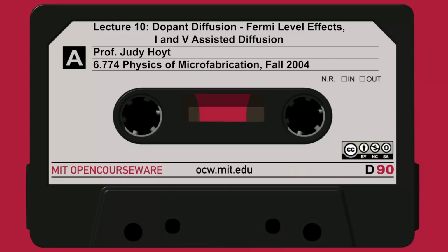By the way, I should say that segregation coefficients, the ratio of some species on one side of an interface to another material on the other side of the interface, sound trivial, but in practice, it's very hard to measure. You might say, well, why don't you just use SIMS? Just profile through the sample and measure the concentration on this side and the concentration on that side. Well, a lot of techniques like SIMS near an interface don't perform very well. Because as you get close to the interface, you're changing the material and the sputter rate starts to change. All the assumptions that you need to make in SIMS tend to be degraded to a certain extent. So you would think we have perfect numbers for this, but we don't. We have rough numbers. And these are the rough numbers that are in SUPREM.